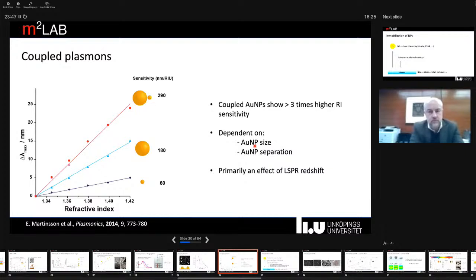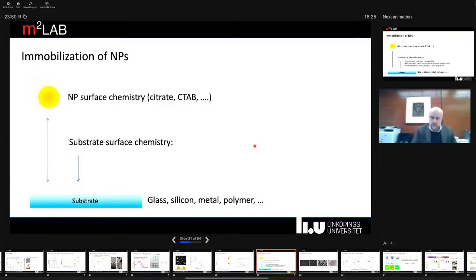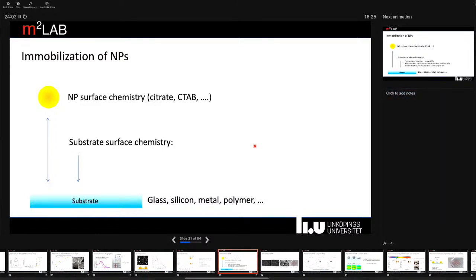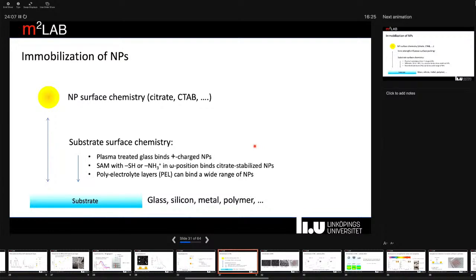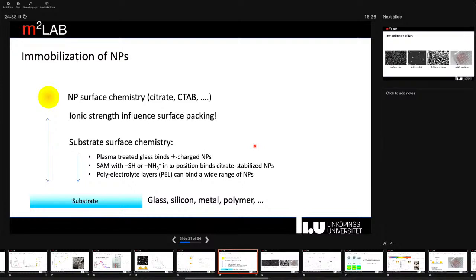And in this case, you probably noticed that we also use immobilized particles, and that's one of the key advantages with refractive index sensing, that you don't have to work with particles that are suspended. There are various ways to immobilize particles, and you can use all sorts of different substrates, such as glass, silicon, metal, polymers. And then you can tune the surface chemistry of these substrates, for example, by plasma treatment, or by self-assembly of monolayers with different terminal functionalities, or just use polymer adsorption in order to bind nanoparticles to the substrate. And then, of course, you can also adapt your nanoparticle surface chemistry to work well for this purpose, as well as modulate the ionic strength to, for example, increase or decrease packing of particles on the substrate.